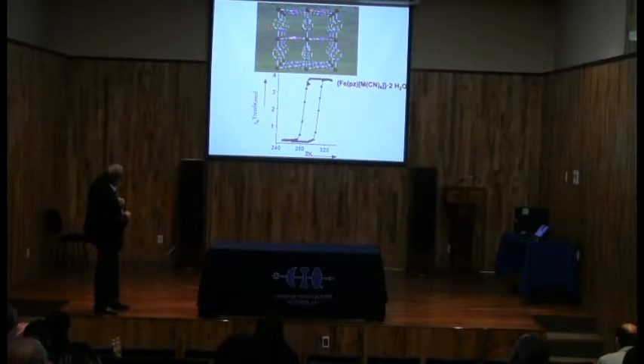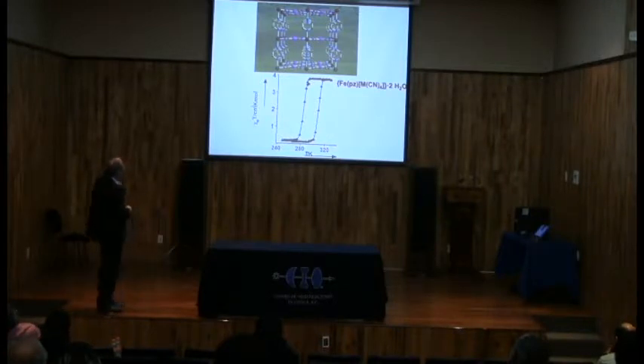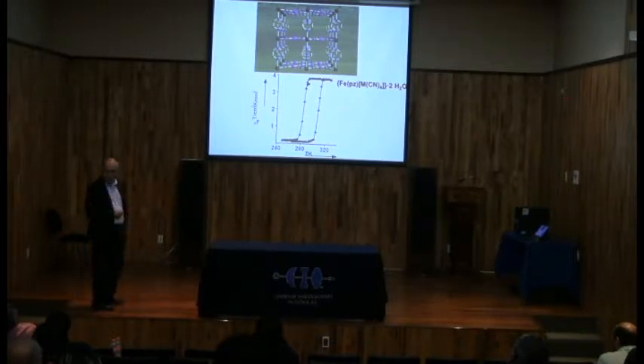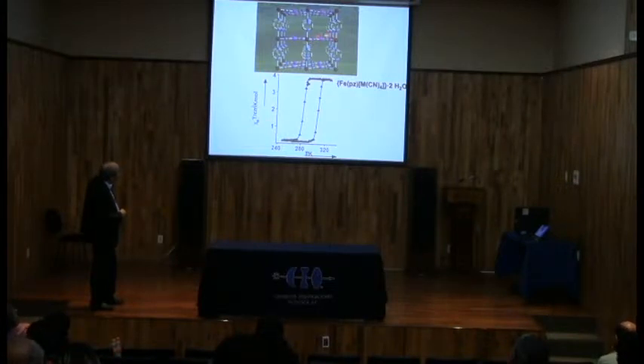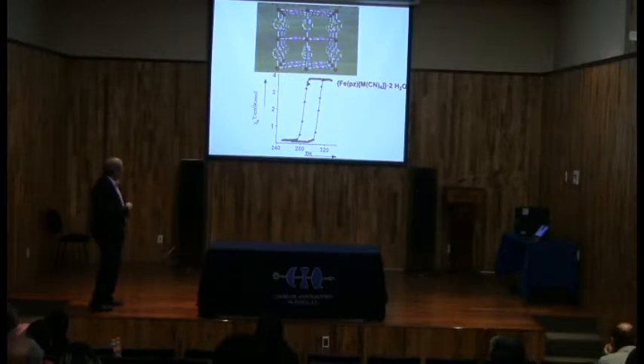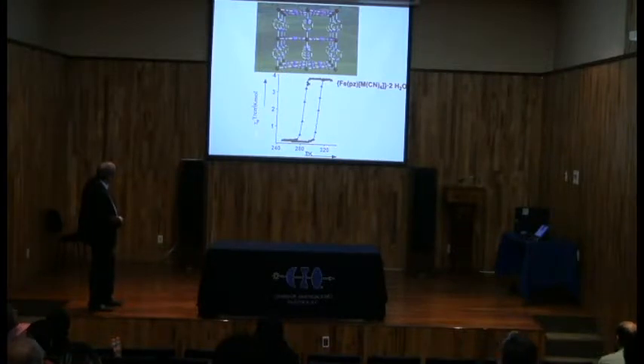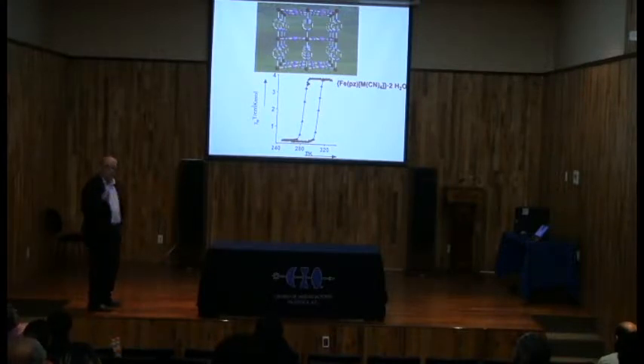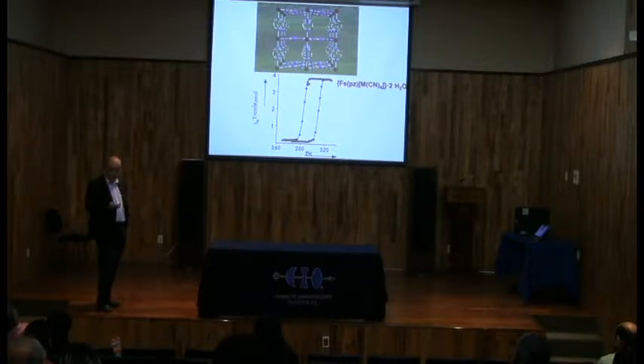The planes are connected by this bond, which is the pyrazine ring, and this is a 3D coordination material, we can say. Because the elastic interactions between the ions are strong, since you have real bonding here, if you measure chi-T as a function of temperature, you will see that the spin crossover is at room temperature, and you also have a hysteresis loop in the system. So you have a memory effect at room temperature.